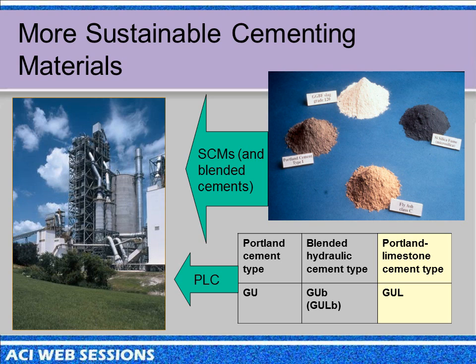So you're not going to trade off fly ash or slag for limestone. It actually increases the replacement of the clinker with the same technical properties, and as I'll hopefully show later, we certainly have a lot of data that shows that the slag and fly ash actually work better with Portland-Limestone Cements than they do with Portland cements, which is interesting.